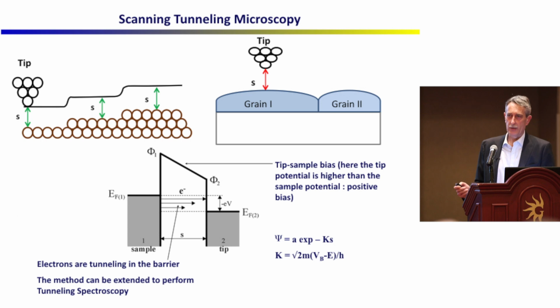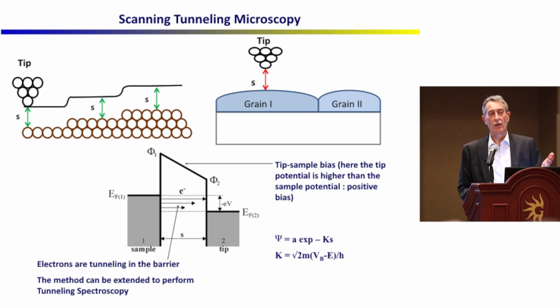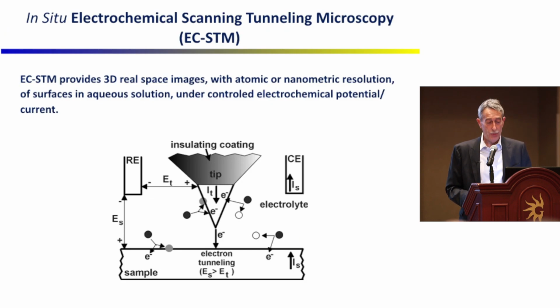Well, I think you all know here that when you do STM, you use a tip that you get close to the surface and scan it so that electrons tunnel from the surface to the tip or vice versa. And this technique provides maps of the electronic density of states. And the electronic density of states is localized on atoms. So ultimately, we have a map of the position of atoms. And the beauty with this technique is that you can use it in vacuum. That's what we do for some application. You can use it in a gas, we also do that, and you can use it in liquid